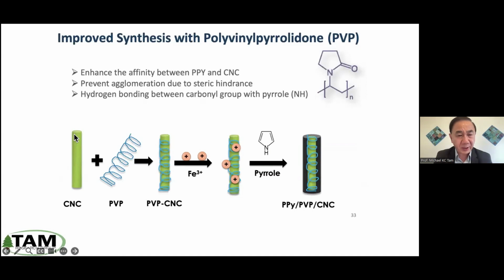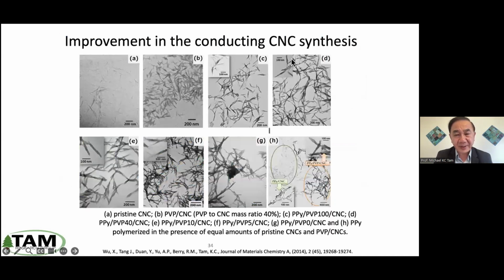properties. So we add polyvinyl pyrrolidone to try to provide an interface that provides good adhesion between the conductive polymers and the CNC. And this reaction is easily done, and we optimized it and found that about 10% coating would give you a very, very good interface to enable the conductive polymers to be polymerized on the surface.